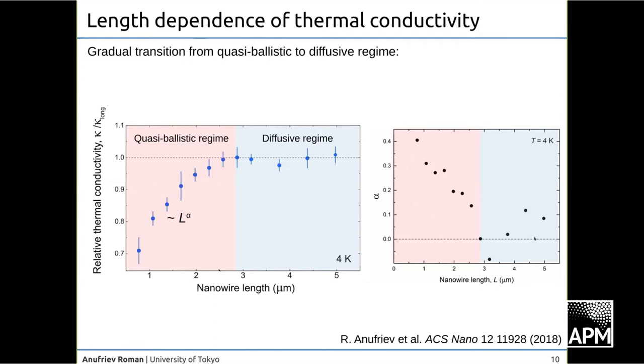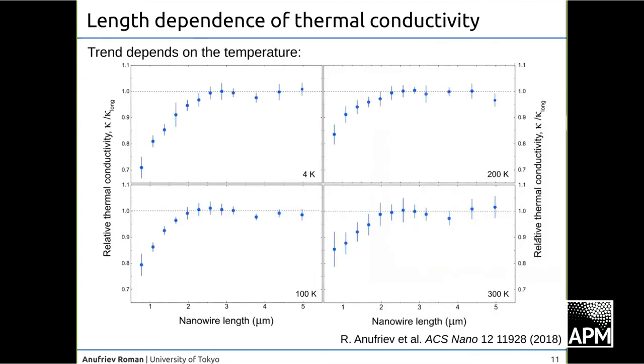So now let us increase temperature and see what will happen. This is what we just measured at 4K, but as we increase the temperature to 100, 200 and 300K, we can see that this curve flattens, and the tail becomes more and more flat, almost flat at 300K. Obviously the error bar also grows at higher temperature, but still some kind of tail we can see even at room temperature, even though it's not so strong.